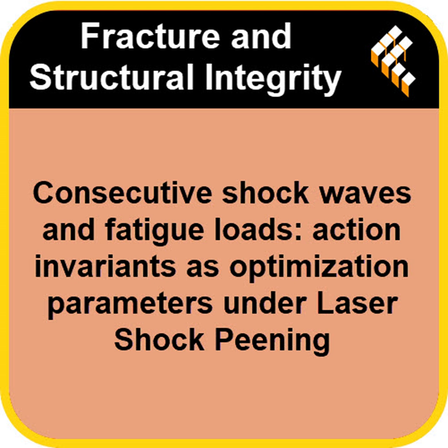They did. They needed to generate a measurable, uniform shockwave over a larger area. The solution was to use plane wave loading on relatively massive targets. Plane wave loading? Yeah, think of it as hitting the material with a perfectly flat impact, not a focused spot. They used a thick plate, about 15 millimeters of AMG6 aluminum alloy. And how did they generate the shock? Not with a laser this time. No, they used impact. They accelerated a thinner 4 millimeter aluminum plate, a flyer plate, up to about 1,400 meters per second.